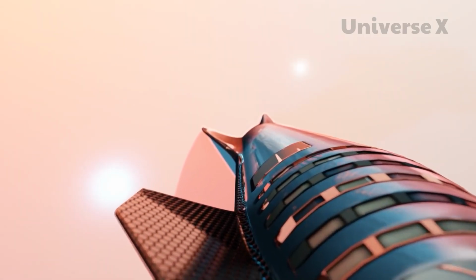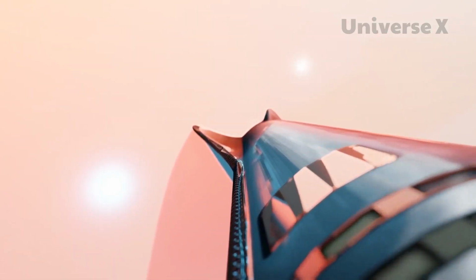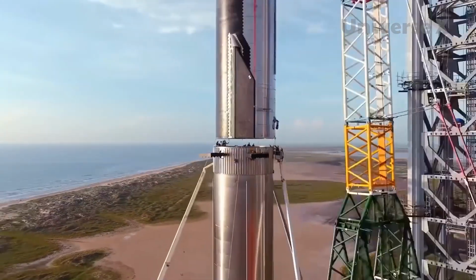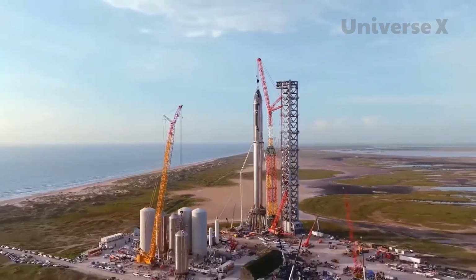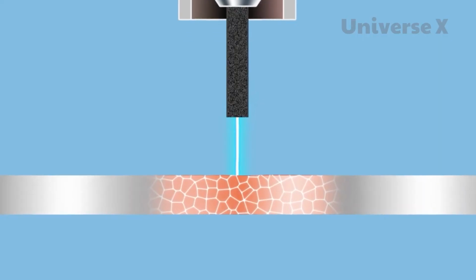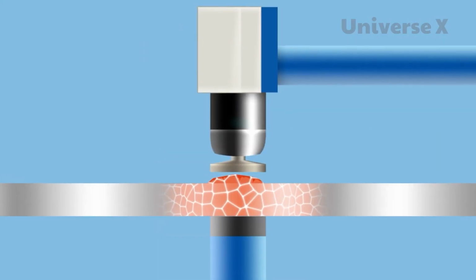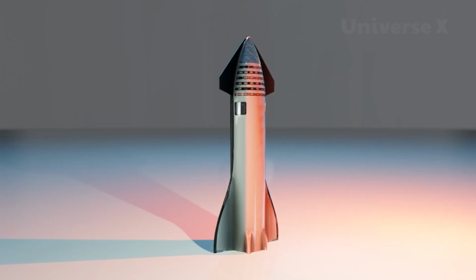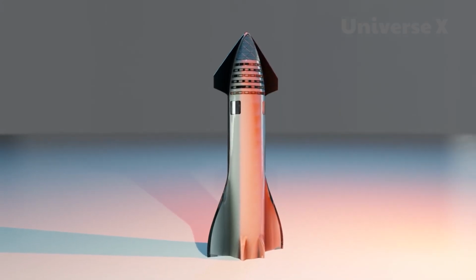However, when the metal is welded, the heat causes the surrounding area to soften. To address this, SpaceX employs a giant planishing machine to hammer the welds down and compress them until they match the hardness of the surrounding metal. This process not only improves the strength of the welds, but also smooths out the finish, enhancing their appearance.